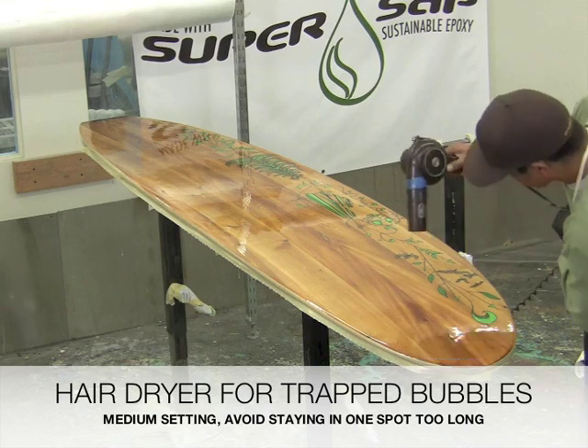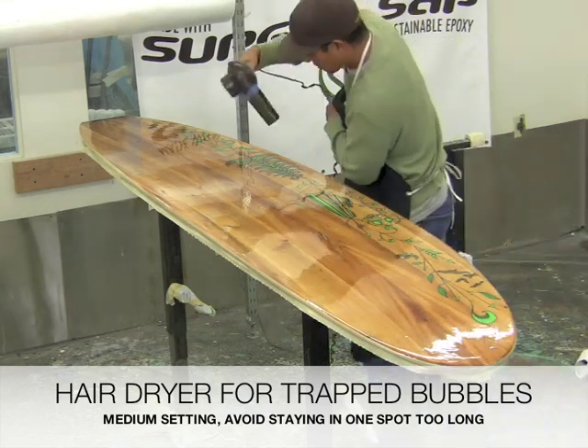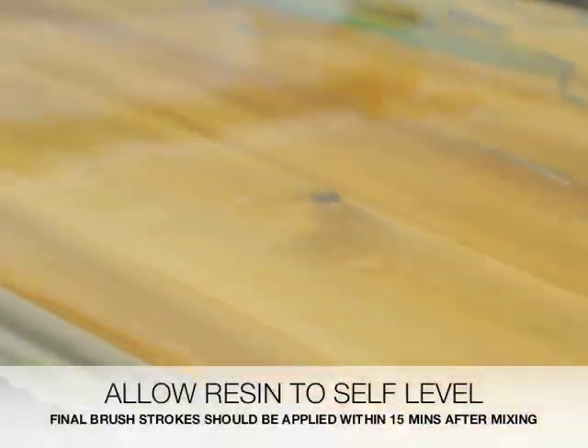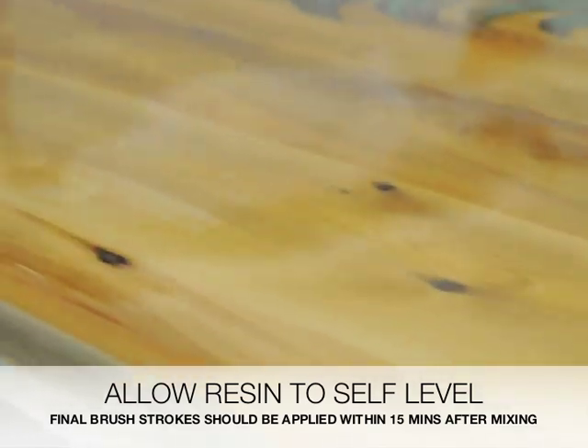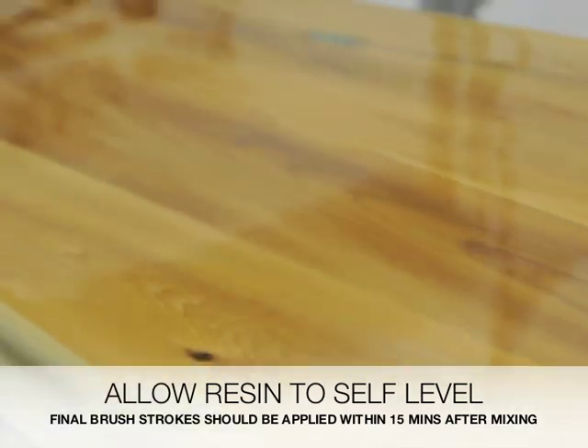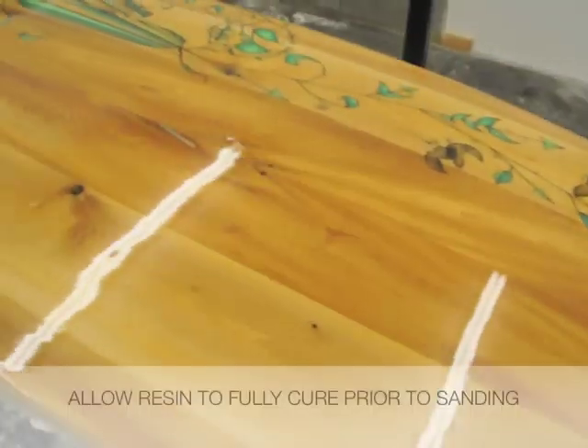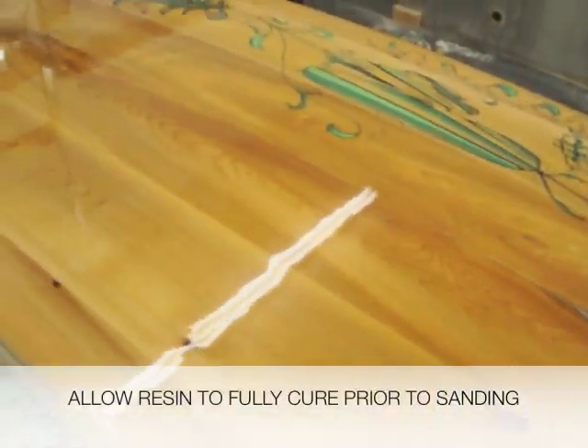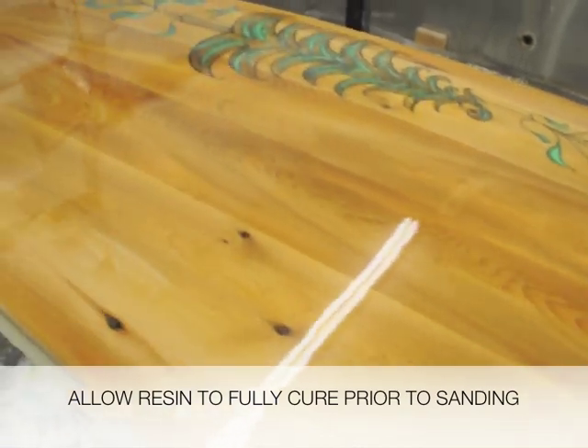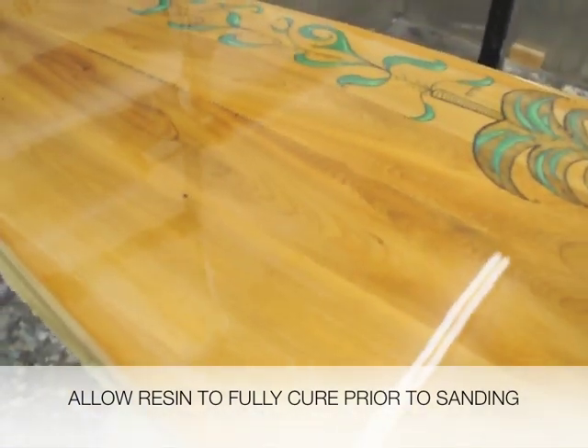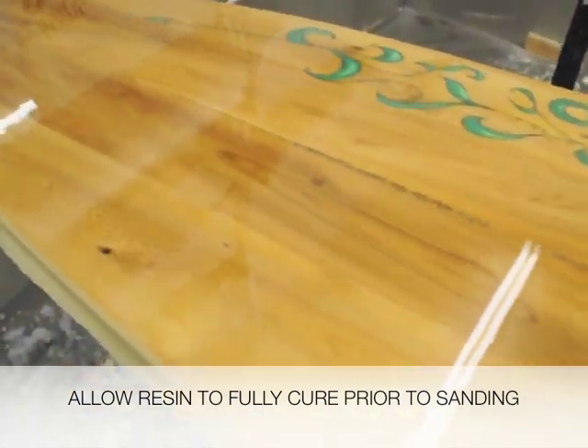Trapped air bubbles can be released by using a hairdryer on a medium setting. Top coats should be applied within 10 to 15 minutes after mixing the resin to allow enough time for the resin to self-level and give a smooth, glossy coating. Be sure that the resin has fully cured to full hardness before sanding.